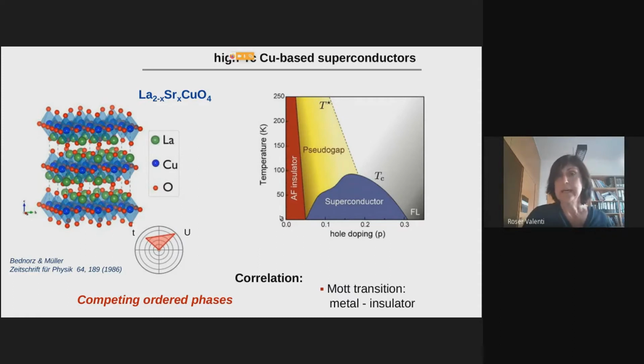And what is interesting is that when we dope the system, for instance, here by substituting the lanthanum cation by another cation, the effect of this substitution is to extract electrons from these copper planes, which means that we are going to allow free states for electrons to start to move. And when this is done chemically, what one observes is that the systems become superconductors, at transition temperatures that right now, I think we are at about 155 Kelvin, which is really very high for a superconductor. So what is important now is how do we describe these materials?